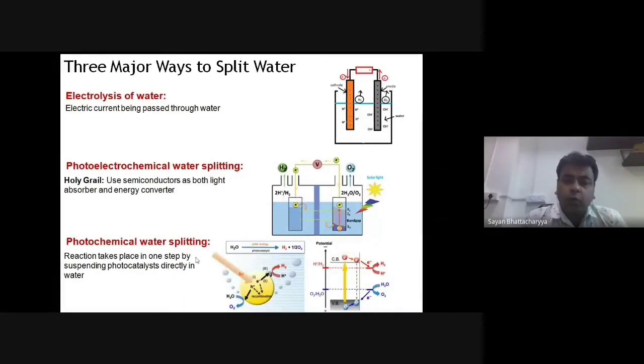Now, the other is photochemical water splitting, which is also observed. So electrochemistry, photoelectrochemistry, photochemistry: electrochemistry is the best according to me, because you can get the largest amount of hydrogen. Photochemistry is slightly the least, because the amount of hydrogen you get is not enough. Here you do not need to apply voltage. There is no question of current and voltage. Simply, you immerse the semiconductor inside the electrolyte, the water, and you should have a co-catalyst like a metal island on top of the semiconductor, where the reduction will take place. And here the oxidation takes place.